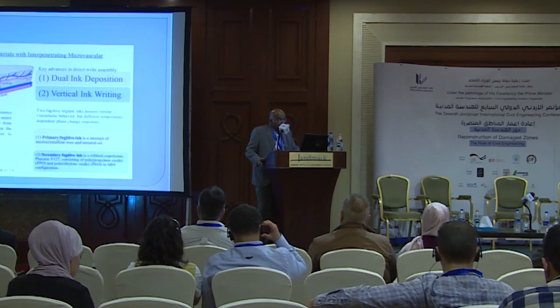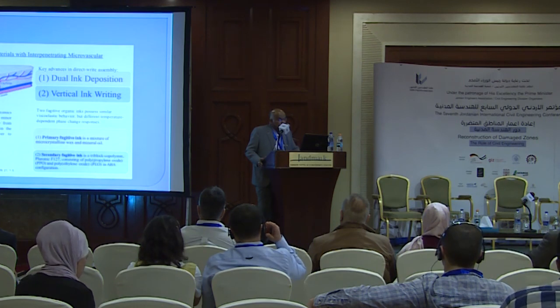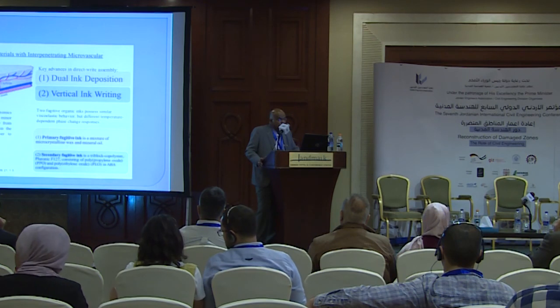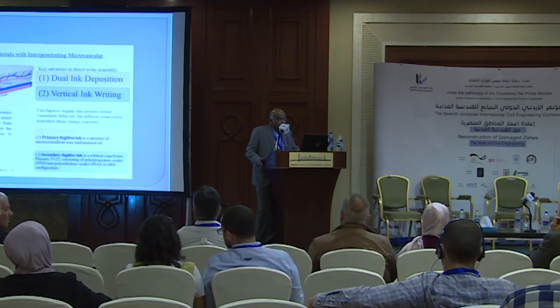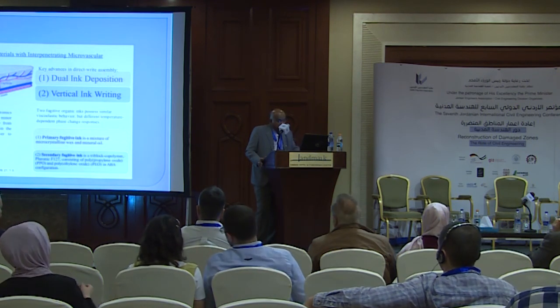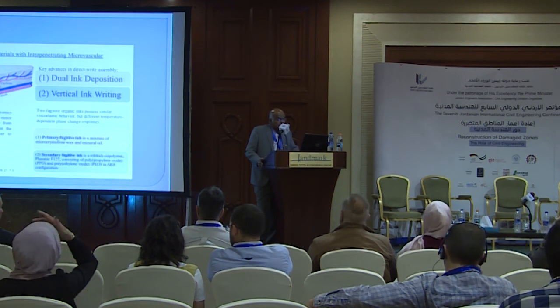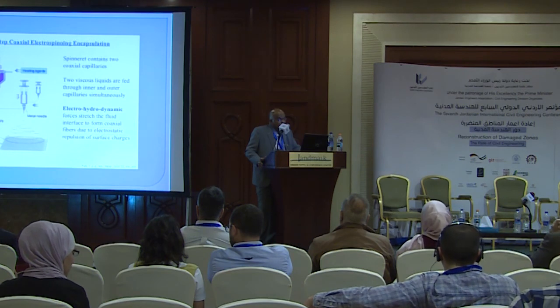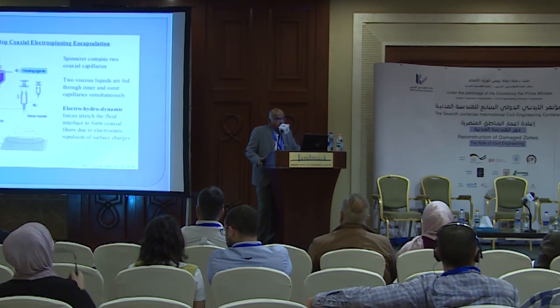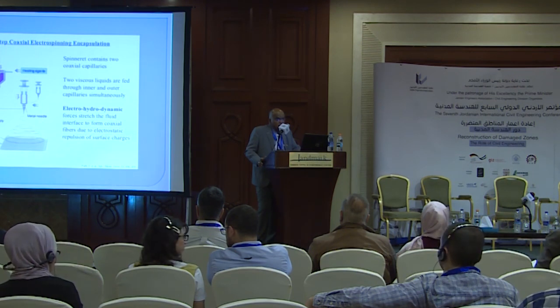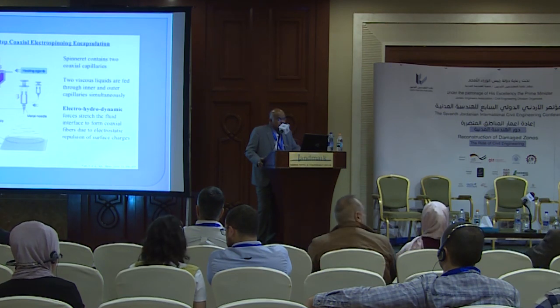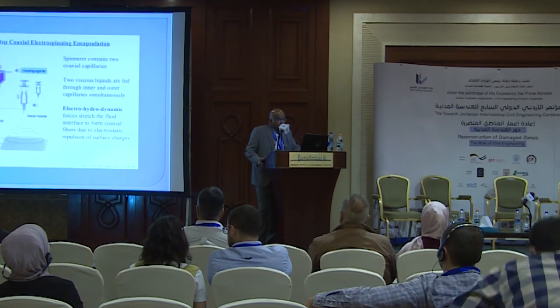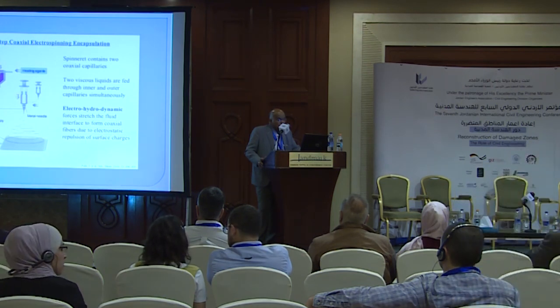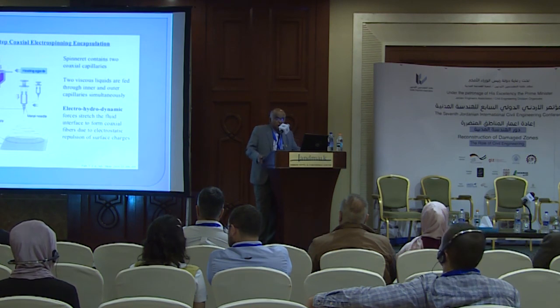And in simulation we use two types of materials, organic inks with a viscoelastic behavior but different time, temperature, phase change properties. So if those are interested, you can see the chemical compositions of these things. So this is another one here by means of electrospinning encapsulation. We have two tubes, a spinneret with two coaxial capillaries. The viscous fluids are fed, and the electrohydrodynamic forces are used to stretch the fluid interface to form coaxial fibers. So you have coaxial fibers which can be filled, the inner space can be filled with the healing liquid.